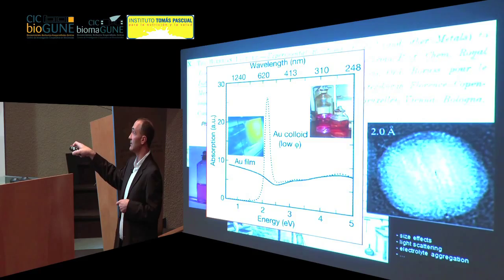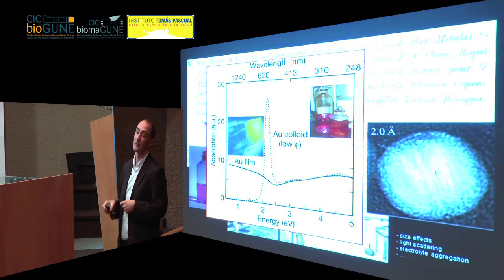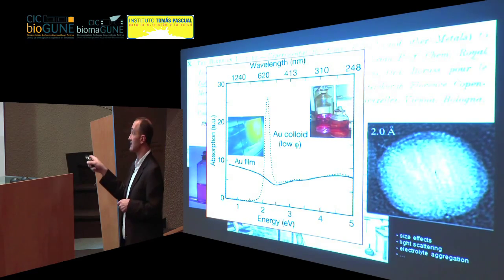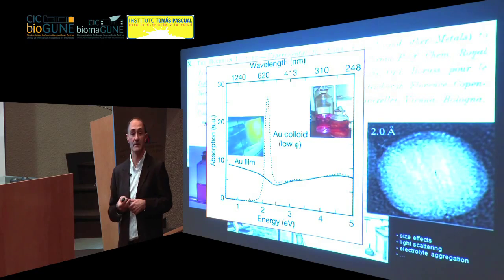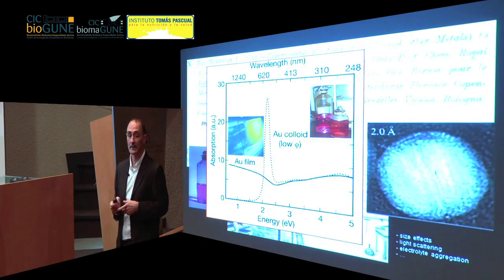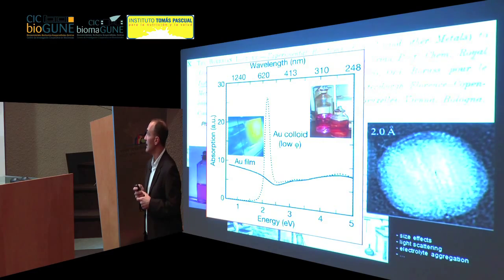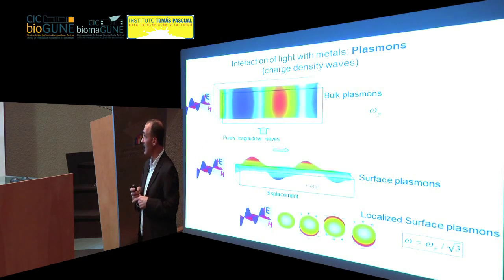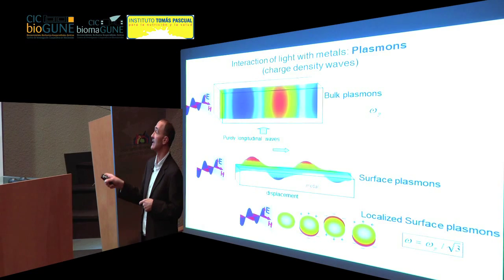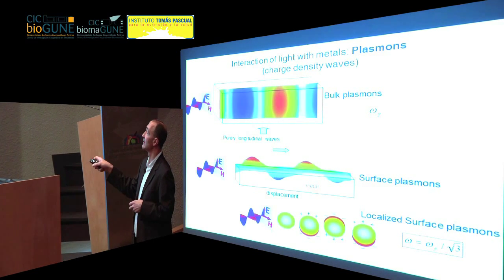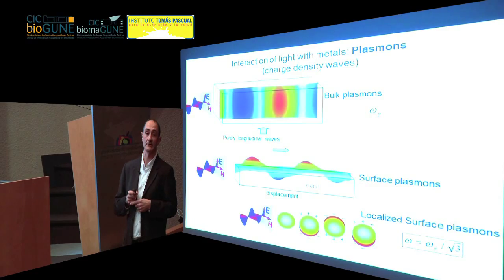And this is why here we have this type of particles, which are perfectly crystalline. And actually, the crystalline lattice is exactly the same as that for bulk gold, but the optical response is completely different. Okay. Now, the reason for these optical effects comes from the effect called plasmon resonances.